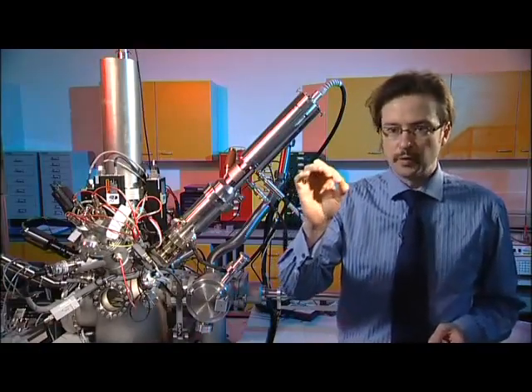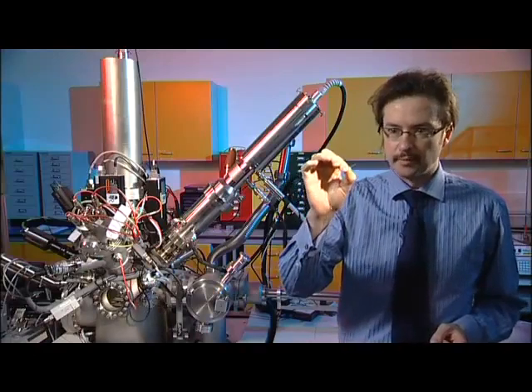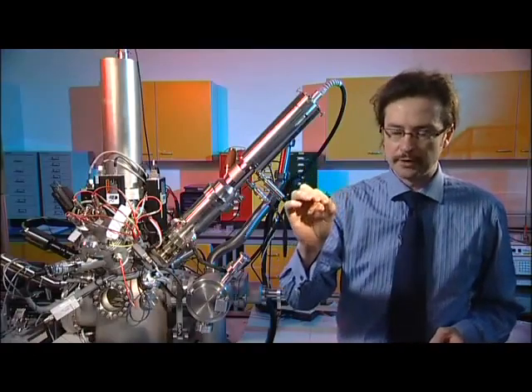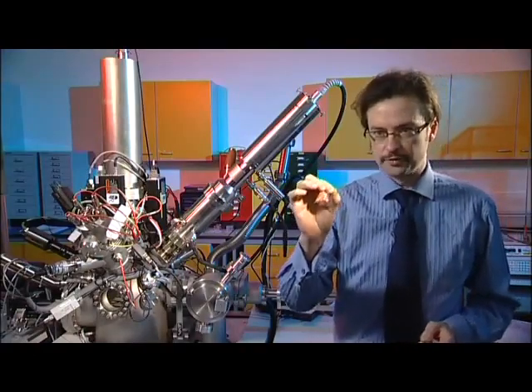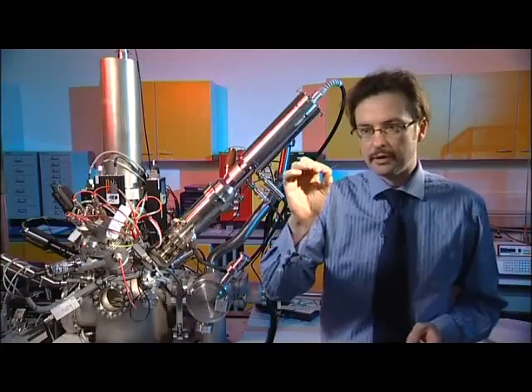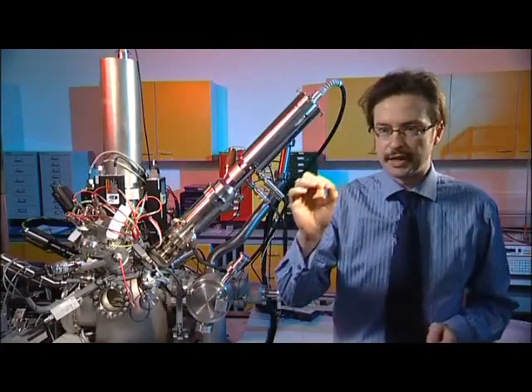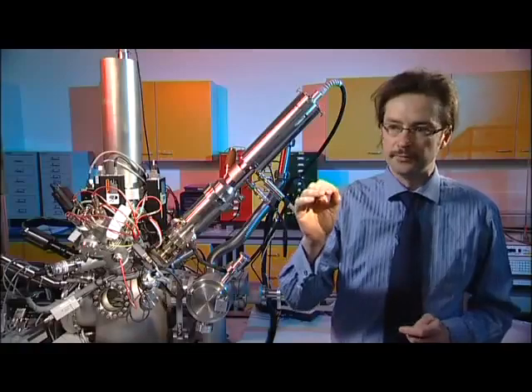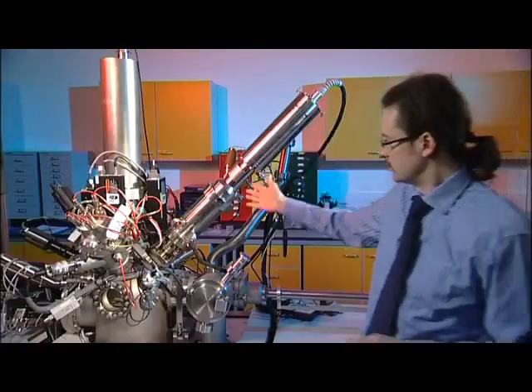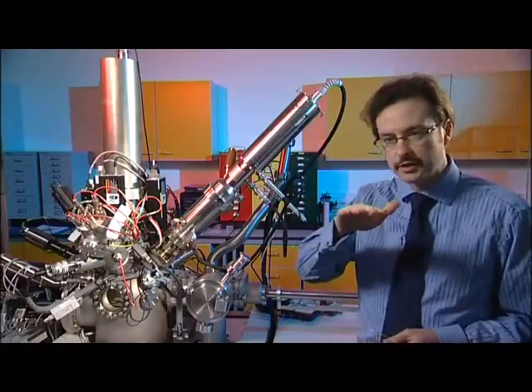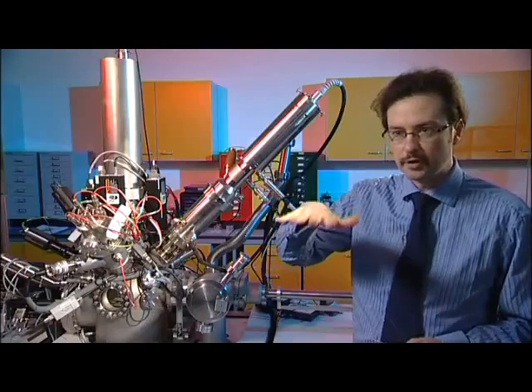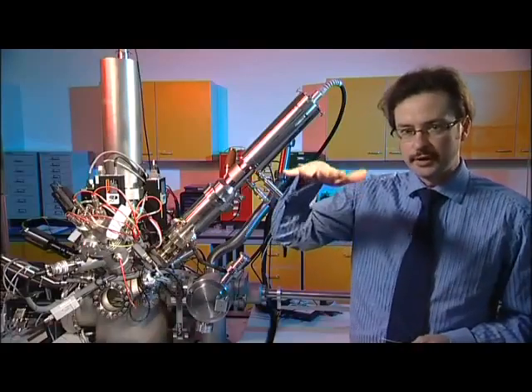What one needs to know is where the drug is loaded in the polymer layer to get the right therapeutic benefit, because what you don't want is to have all the drug at the surface or at the interface with the metal. One needs to have a nice controlled release profile. Using this instrument here, using the C60 profiling, we can actually map out where the molecule is, the active molecule, in these 100 nanometer layers of polymer.